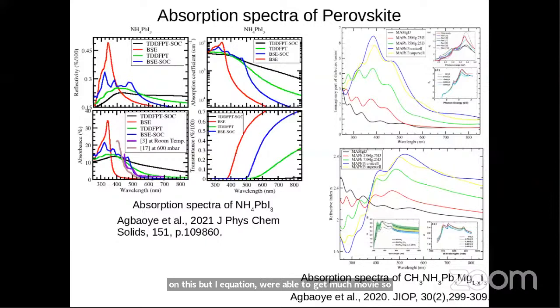So in 2020, we also looked at the fact that since lead is said to be toxic, we can dope lead with magnesium. So we did that with a lot of configurations where we have lead at 25%, magnesium 75%, lead 75%, magnesium 25%, and we have a whole unit cell of methylammonium lead iodide, a whole unit cell of methylammonium magnesium iodide. So with that, we're able to check the absorption spectra, and here we were using TDDFT, and also we are able to realize that the peaks on the experimental results are reproduced by TDDFT for methylammonium lead iodide, which we can find the references, and also we're able to do the same thing for refractive index. We're able to reproduce the peaks and have a very good result with absorption coefficients.